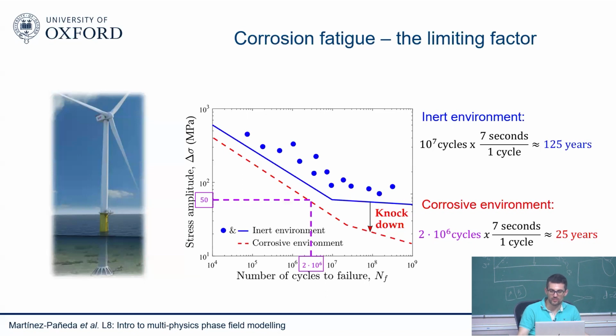So that's another problem. There are also various problems related to the fact that you normally deal with welds: you have material heterogeneity, residual stresses, sharp stress concentrators. These SN curves deal with smooth samples, and you cannot simply account for the stress concentration factor because, again, there's an interplay with corrosion. Corrosion is accelerated by mechanical fields, so you really need to solve the problem, and that's a complicated problem because we don't fully understand corrosion fatigue. And as you see, you are modeling things that fail over millions of cycles.